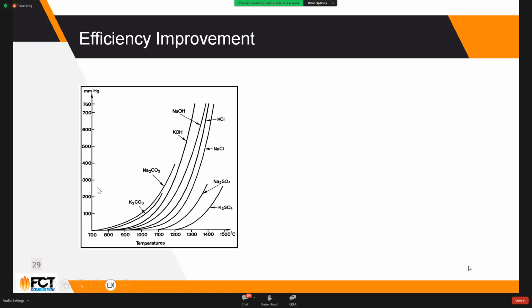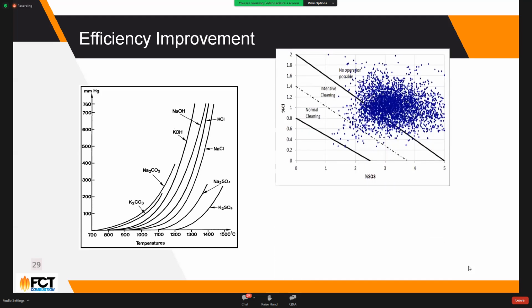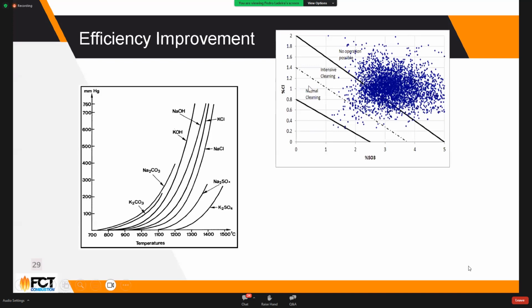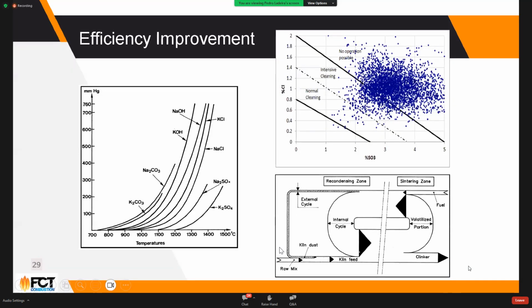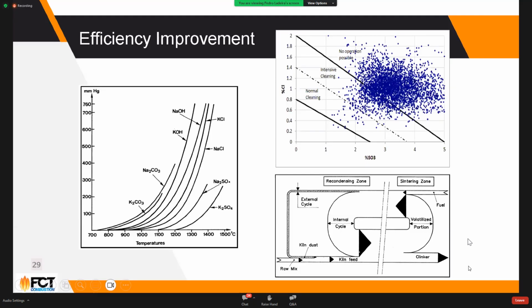When you know what you're doing and you balance all the elements entering the kiln, you can really get to an equilibrium between sulfur and alkali, and by that you can reduce the sulfur cycles, and then you can prevent the formation of rings and all this difficulty you may have in the process. And also you can prevent yourself from clogging the preheater and really control the internal cycles of those nasty elements that used to be in the cement industry, in the clinker kiln.